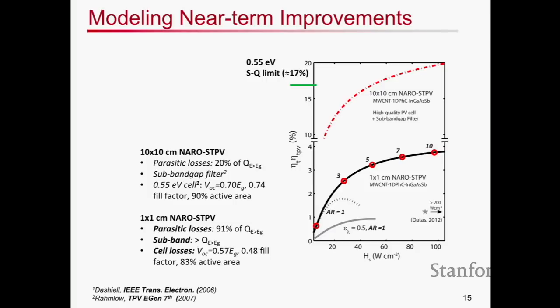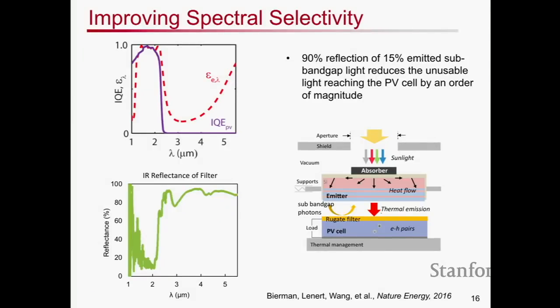And so we've been working on these indium gallium arsenide antimonide cells. But we believe as we scale up this device, there is significant potential. With this study, we were able to say that there are still a lot of losses. There are certain photons hitting the PV cell that are not useful for the conversion process, and they get converted to waste heat, essentially. So our next step was thinking about how we can take advantage of those photons that are not being useful to the conversion process.